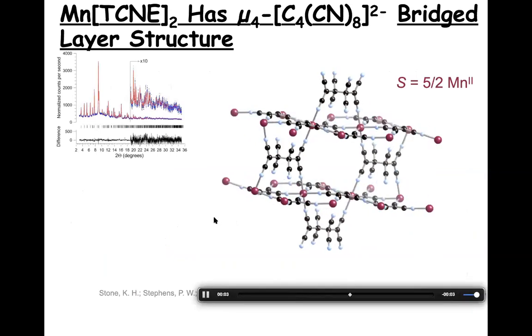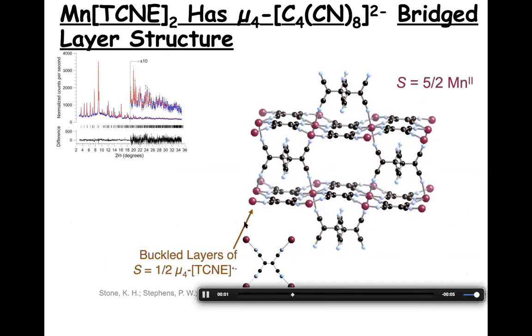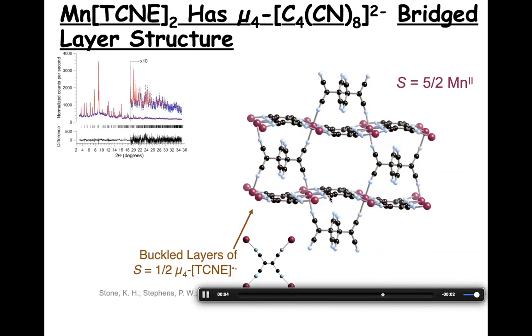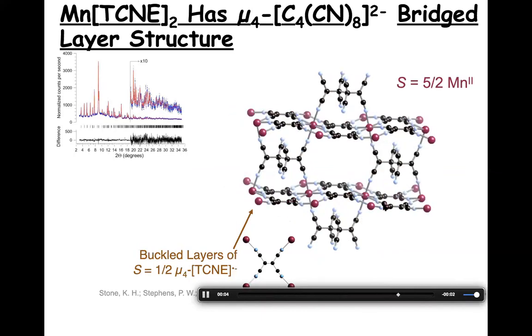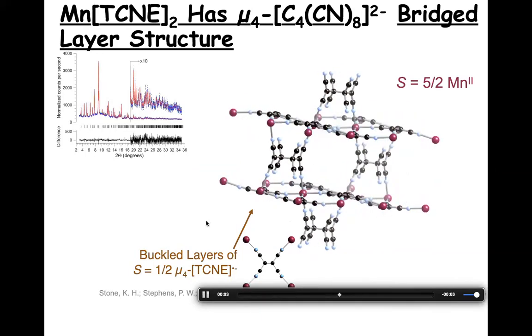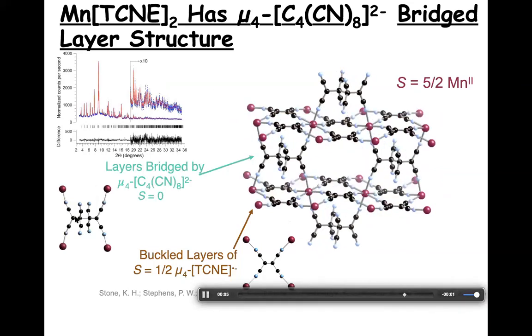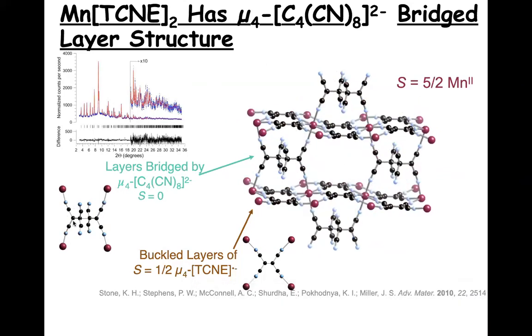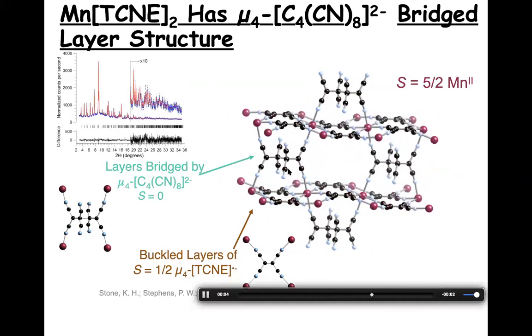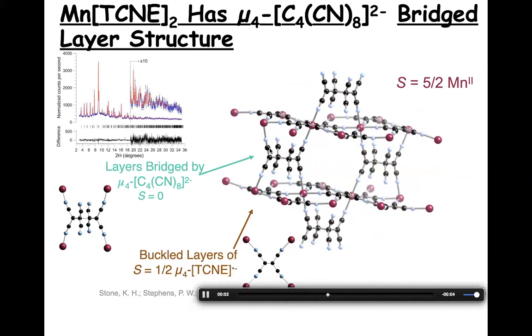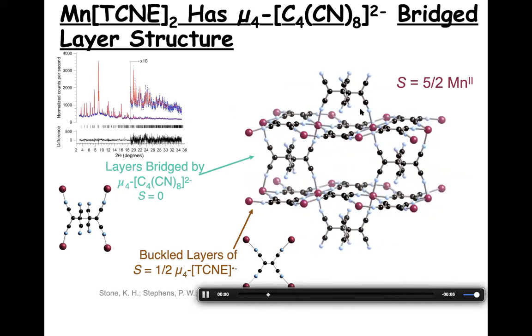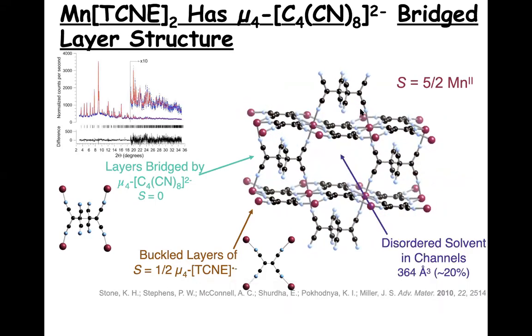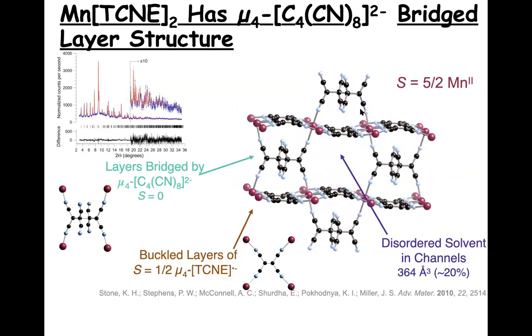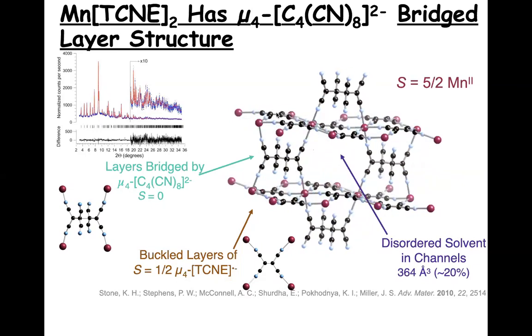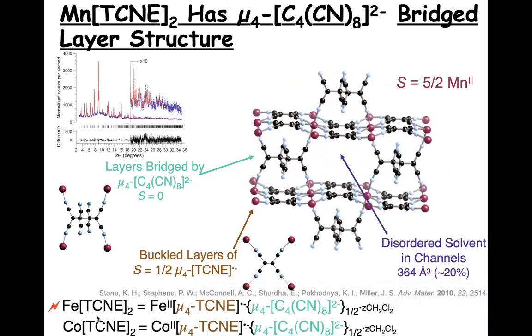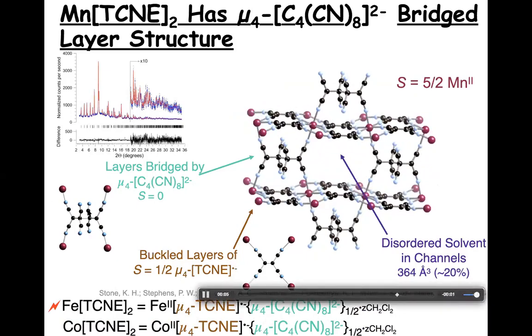The structure of this has been determined by powder diffraction, and it has layers of TCNE bridging 4 manganese II sites. And these are layers that we will recognize as being ferrimagnets, which I'll come back to later. And bridging the layers actually is the dimer of TCNE, octacyanobutane dianion, which is diamagnetic. So these magnetic layers are interconnected through these nitrogen, carbon, carbon, carbon, nitrogen links to bridge this 3-dimensional network structure. And there's a little solvent in here, about 20% of the volume of the structure, floating in and out. So the overall composition of this material of 2 TCNEs is in fact 1 TCNE and a half of the dimer of TCNE.